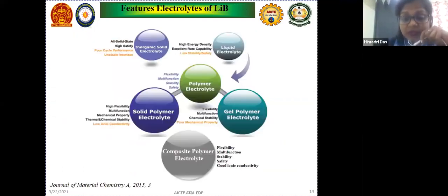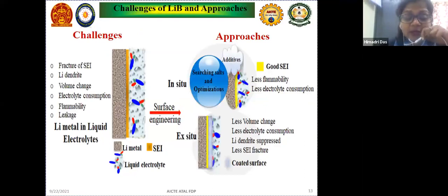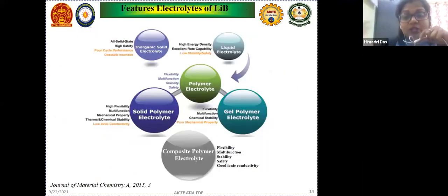The major thing is to avoid the disadvantages of liquid electrolytes, so people are focusing on different types of electrolytes like inorganic solid electrolyte, liquid electrolyte, polymer electrolyte, or sometimes composite electrolyte, like mixing the solid electrolyte with gel electrolyte. If we see such varieties of electrolyte, each has its pros and cons. Inorganic solid electrolyte, even though it is a solid electrolyte with high safety, has issues like poor cycling or poor performance. Instability happens in its interface.